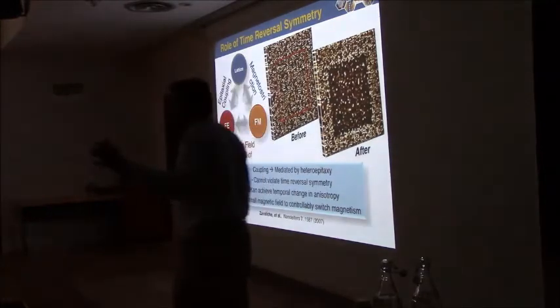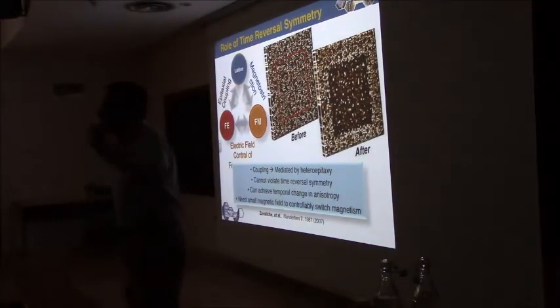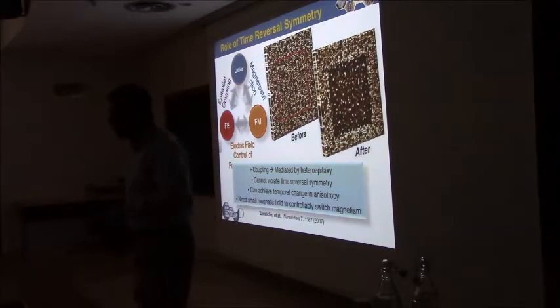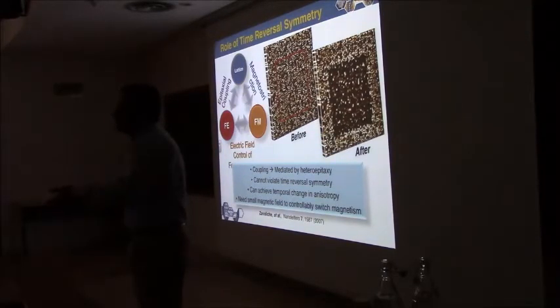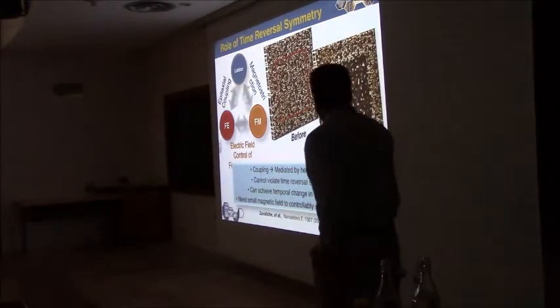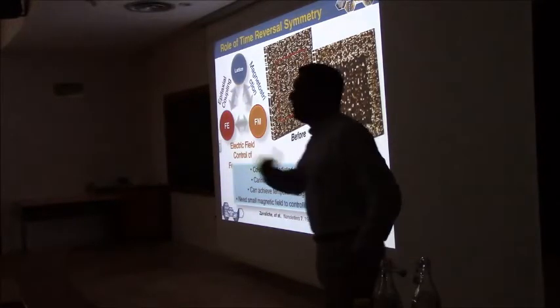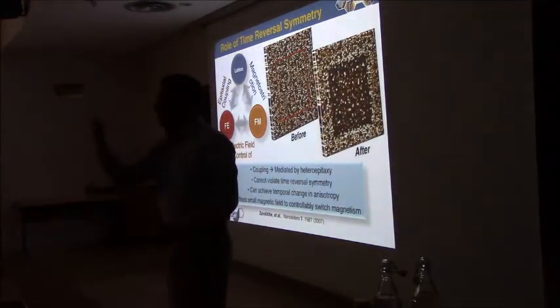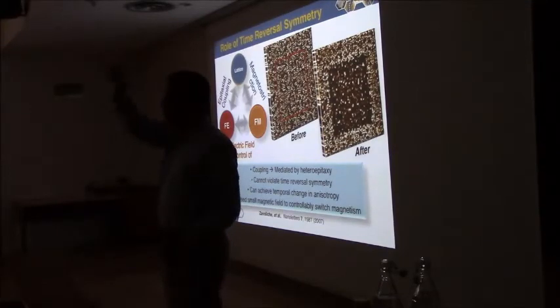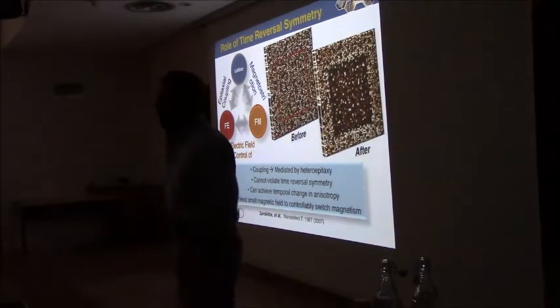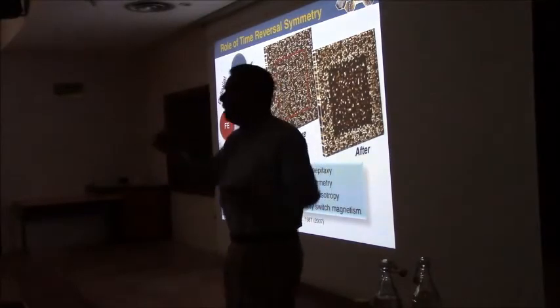Why is this important? Because as we go through, if you're going to be using electric field, which doesn't break time symmetry, obviously, to control something which is magnetic in nature, you have to be really careful about this. Therefore, in terms of interpreting your data, you have to be very, very careful. So keep that in mind. So you can't violate time reversal symmetry. If you're only manipulating magnetism, if you're doing this, it's okay. But if you're going from this to this, you have to be very careful. You can manipulate, meaning you can wiggle it by simply changing its anisotropy a little bit. Okay.